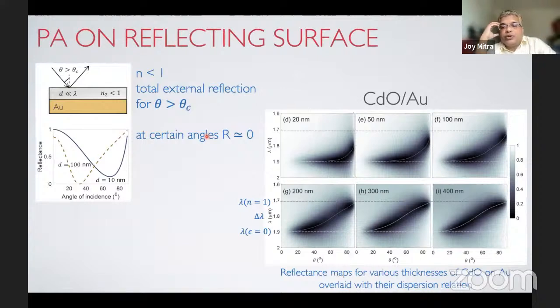For this part of the work, we chose another material in the same class, cadmium oxide on gold. And if you look at the reflectance map of these very thin coatings, we see there are regions of very high absorption, very low reflectivity, even for films as thin as 20 nanometers, 50 nanometers, 100 nanometers to 400 nanometers. Remember, we are doing this in a wavelength range of something like 1500 nanometers, and these are way below the lambda by 4 limit.